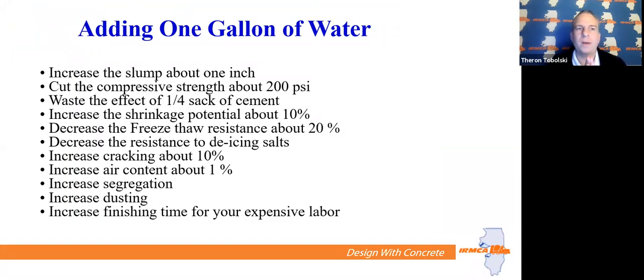These are some rules of thumb, right? Adding 1 gallon of water to 1 yard of concrete will increase the slump by 1 inch. It'll cut the compressive strength by 200 PSI. It wastes the effect of 1/4 sack of cement. It'll increase the shrinkage potential by 10%. Think about that for a minute. 1 gallon of water increases the shrinkage potential by 10%.